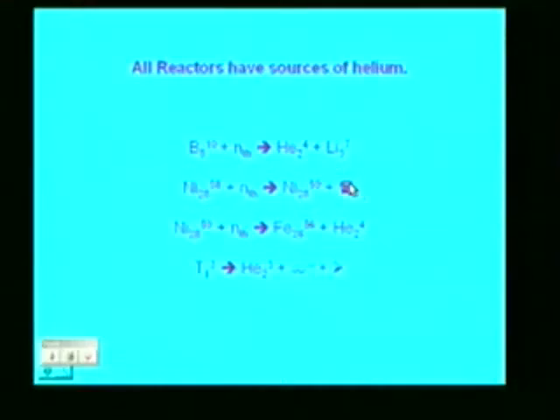The next pair reaction is more interesting because it's a two-step reaction. Nickel 58 is a common isotope of nickel. It's about 63% abundance. It absorbs a thermal neutron to form nickel 59. The product is a gamma. Nickel 59 also has a significant thermal neutron absorption cross-section, and it leads to iron 56, the common stable isotope of iron, and an alpha particle. So this can be a very significant source of helium in a thermal reactor.